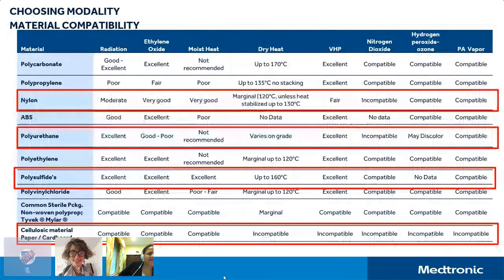What I can do here is look at the materials and break them down into different modes of materials that we use for making our medical devices. Highlighted are some of these: nylon, polyurethane, polysulfides, and cellulosic material. If you look at the first 3 columns, which are the standard modes, the compatibility is rated as moderate to very good. However, when you are looking at the new technologies that we are trying to adopt, sometimes there is no data, and sometimes it ranges from poor to excellent.